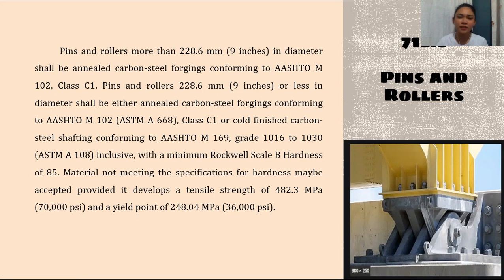The material not meeting the specification for hardness may be accepted provided it develops a tensile strength of 482.3 MPa or 70,000 psi and a yield point of 248.04 MPa. So, material that does not pass the specification stated in AASHTO M169 can still be accepted provided its tensile strength reaches 70,000 psi and its yield point is 36,000 psi.